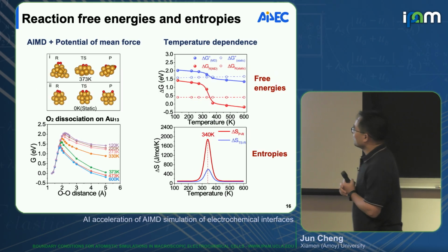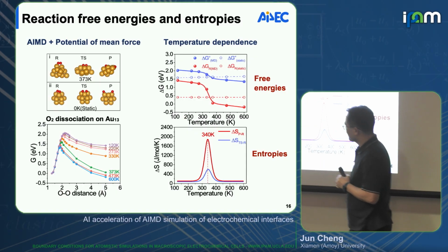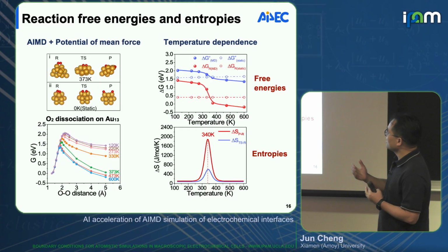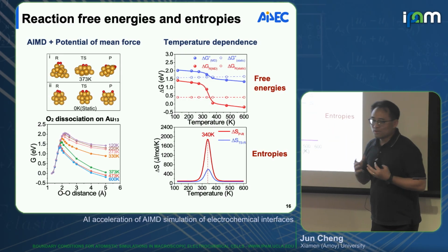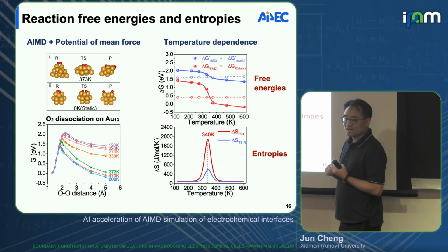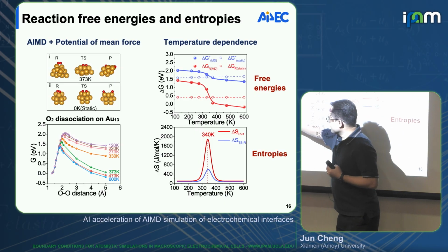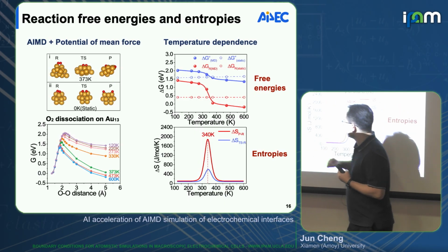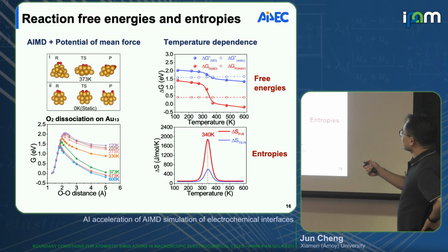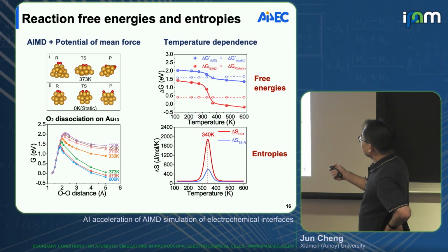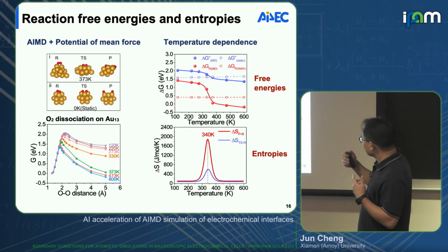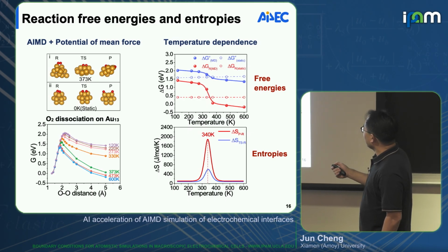An early example we did is the oxygen dissociation on a gold 13 cluster, a very small cluster, but just applying ab initio molecular dynamics and enhanced sampling technique, we can calculate the free energy profile for this reaction. And when we do molecular dynamics, of course, we will have temperature, which is missing in the standard DFT calculation. So we calculate the free energy profile at different temperatures. Just to show here, the red curve is the free energy change as a function of the temperature, and the blue curve is actually the free energy barrier. The trends are similar. Let's just focus on the red one.